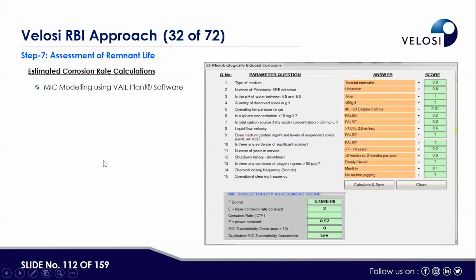MIC is a microbiologically induced corrosion model available. So we have to provide the applicable conditions, and then we can see the susceptibility, whether maximum 10 or 0, and based on the F factors, we can see what is the probability of the MIC, as 1 is the low at this.